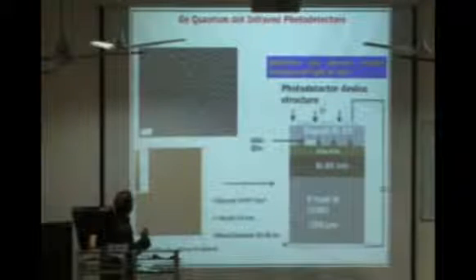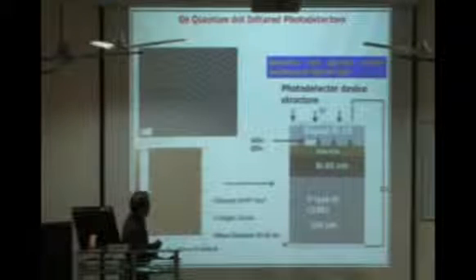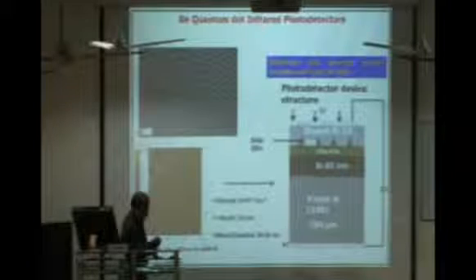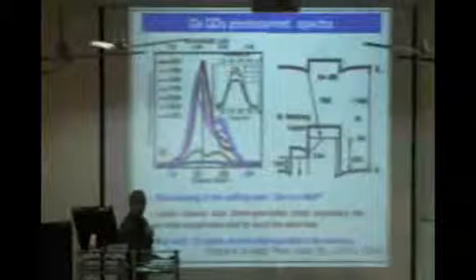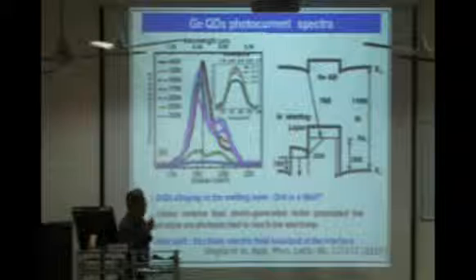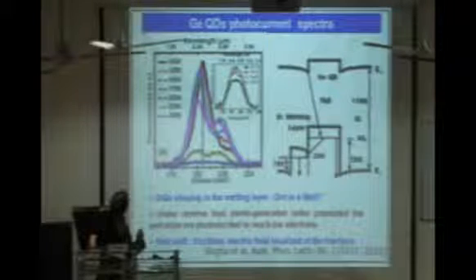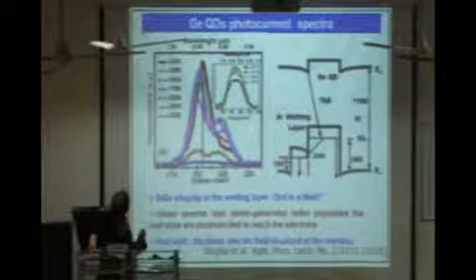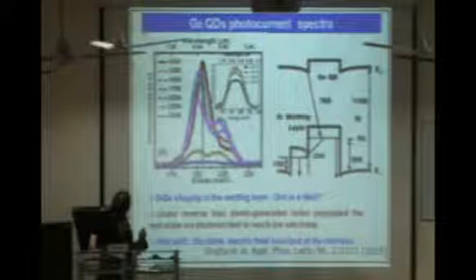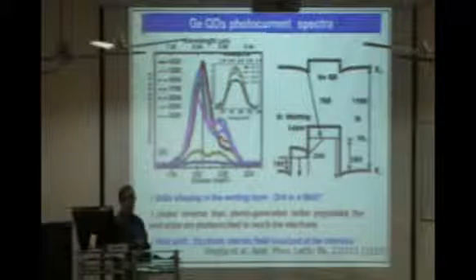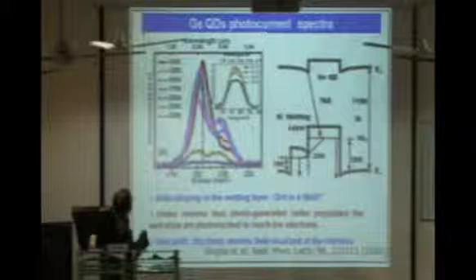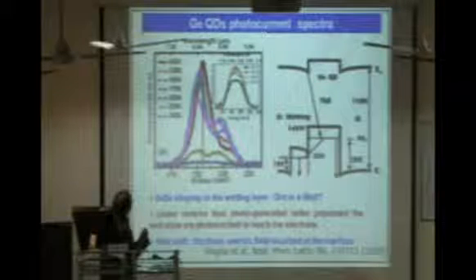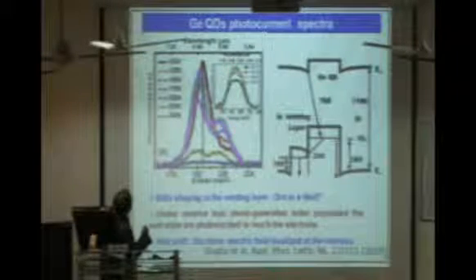So what about the quantum dots that we grow in our MBE? They are very large area quantum dots. In the structure, we put a silicon substrate, and then we put some dopants into it. And finally, we got a response in the so-called mid-infrared range. We are trying to make a mid-infrared detector where the typical good wavelength is between 8 to 12 microns. But with our quantum dots, we got good photo response only at about 6 to 7 micron wavelength.